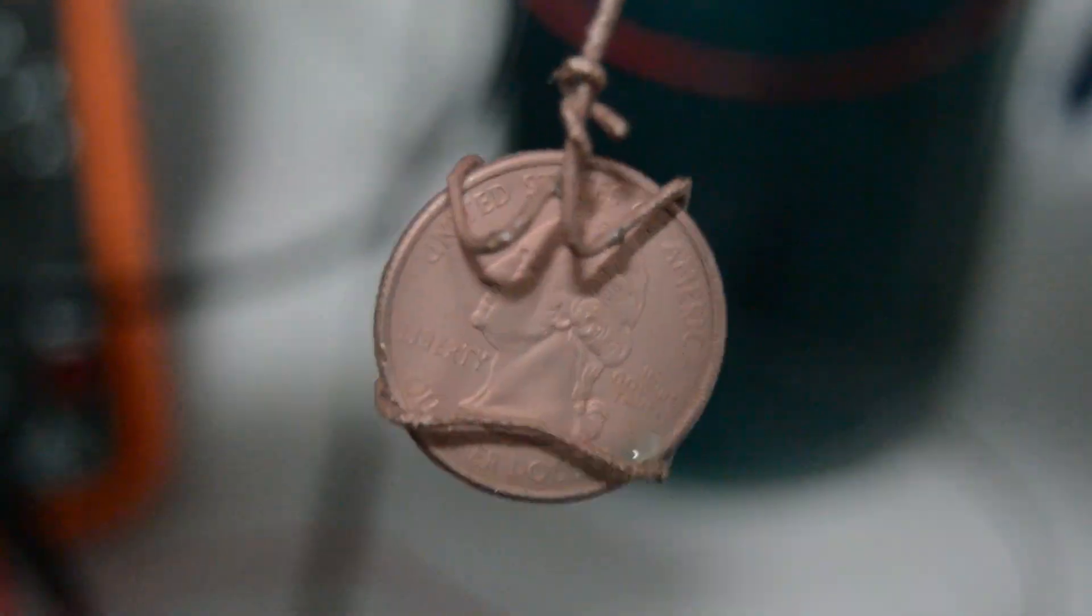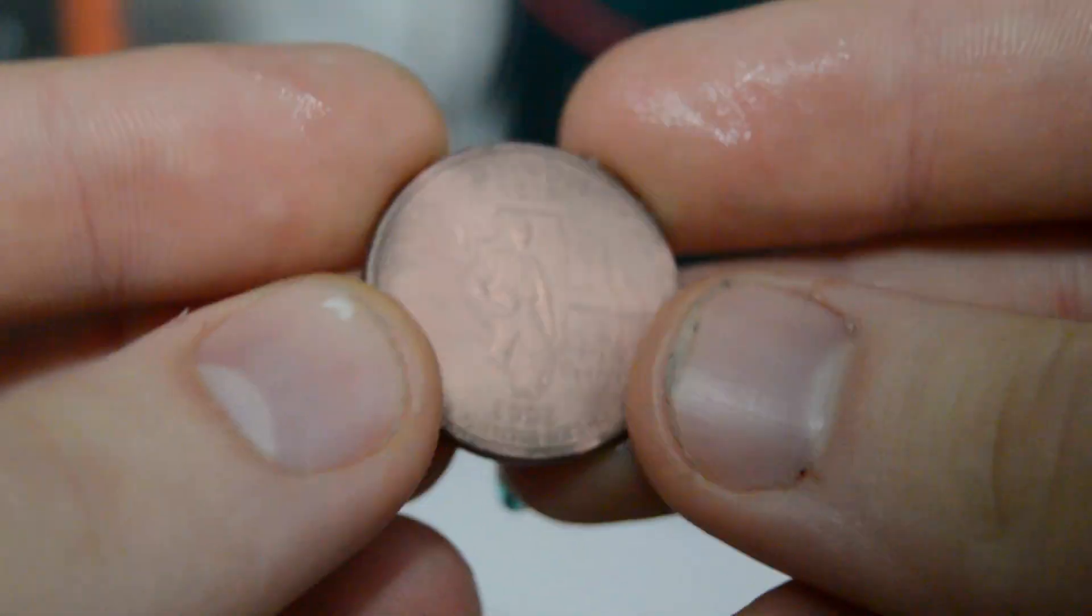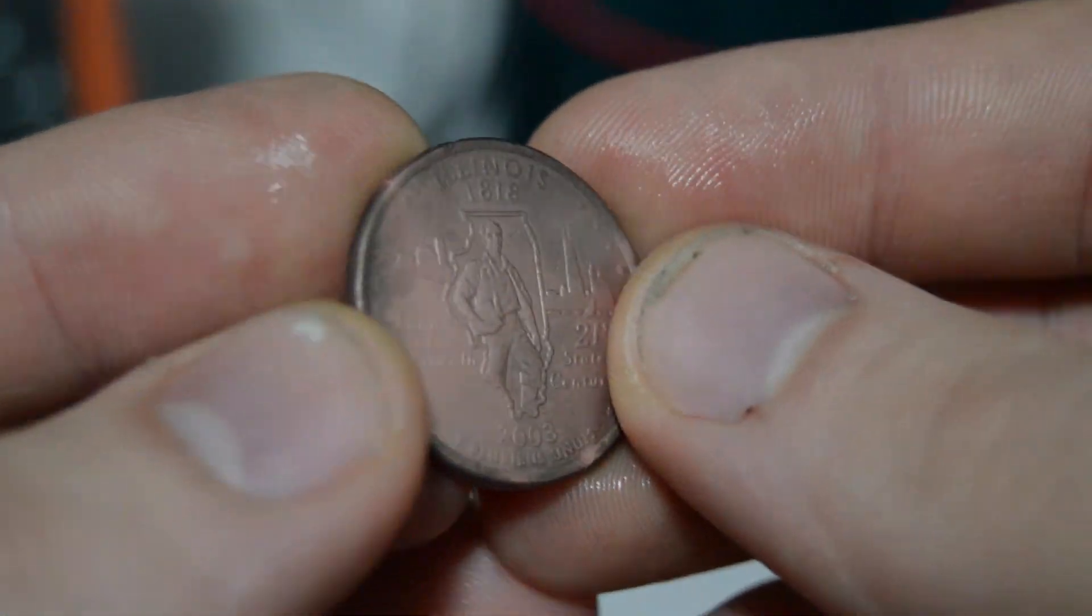I did not immediately clean off the electrolyte, and you can see that the surface gets progressively brown from oxidizing copper. That being said, if you want to have bright orange copper colored parts, make sure you rinse them thoroughly immediately after removing them from the plating bath.